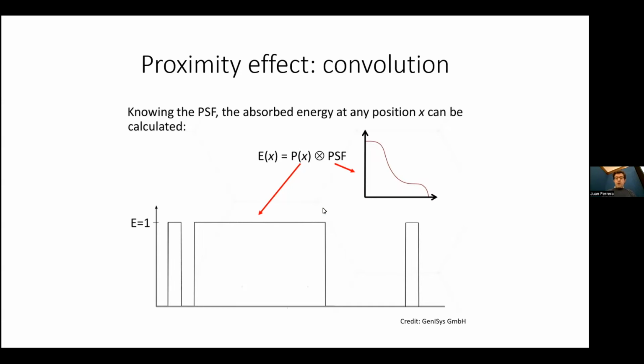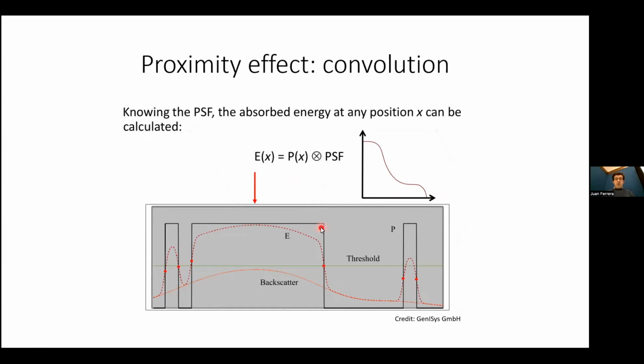So once you do the convolution, you will end up with energy deposition that looks like the red dotted line. You can see there's also the backscatter component here. And also the forward scattering means that the slope here is not an impulse or a step like you initially designed. So you have blurred edges due to forward scattering, and then you have a background exposure due to the backscattering.